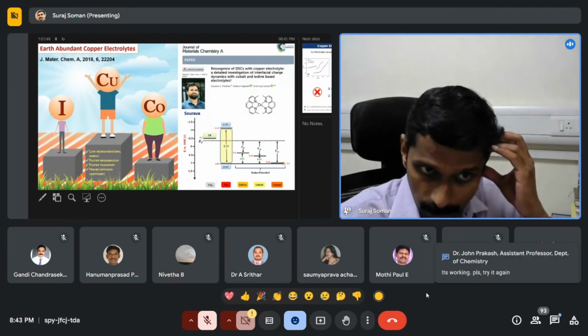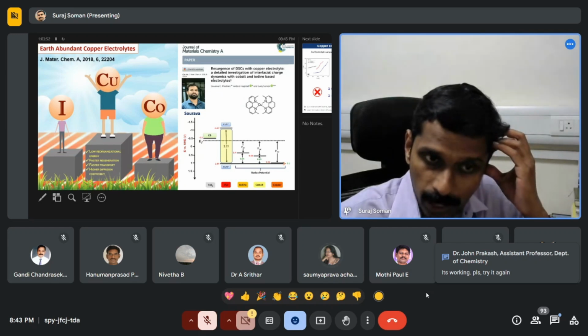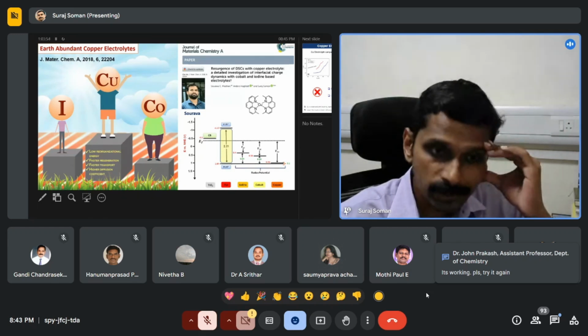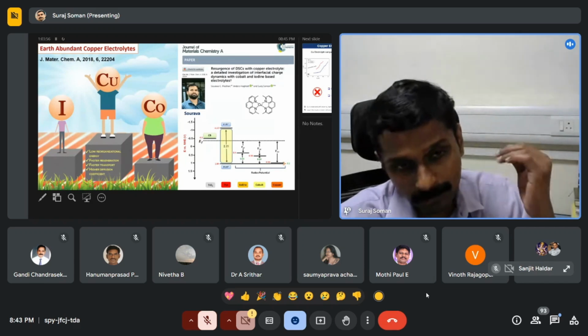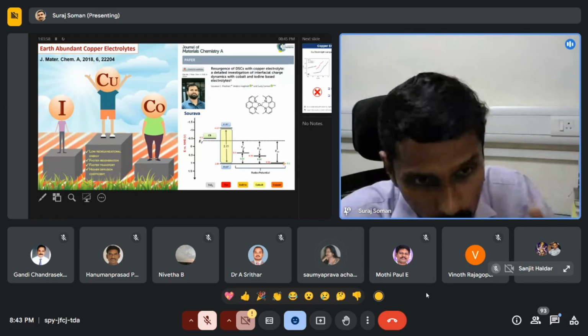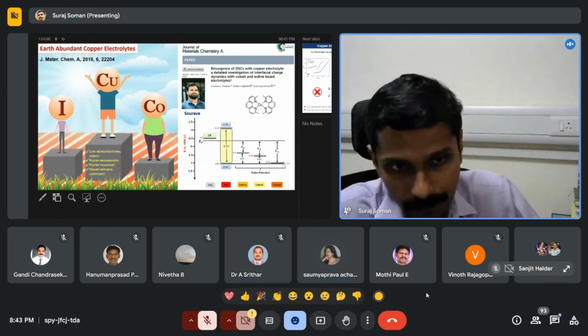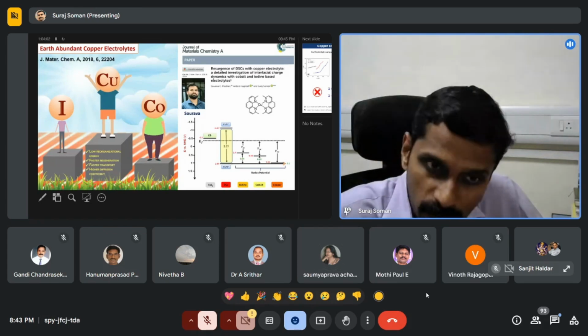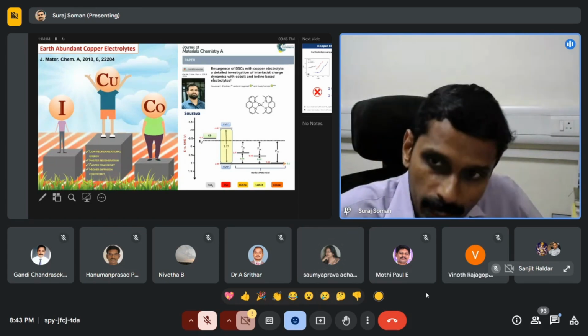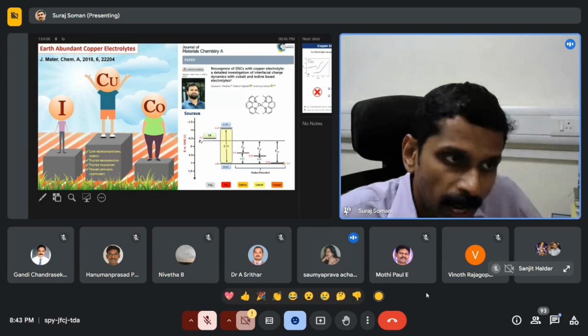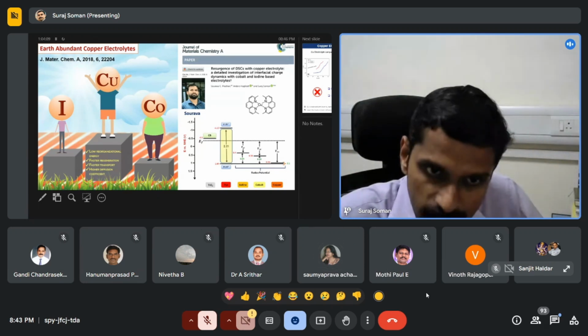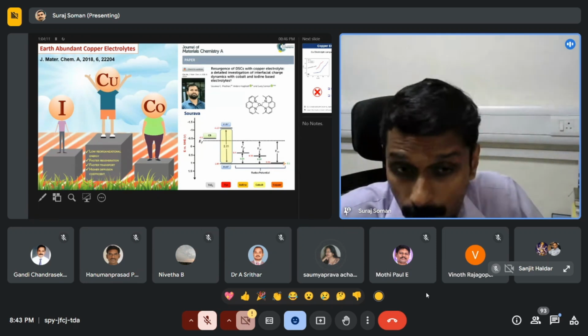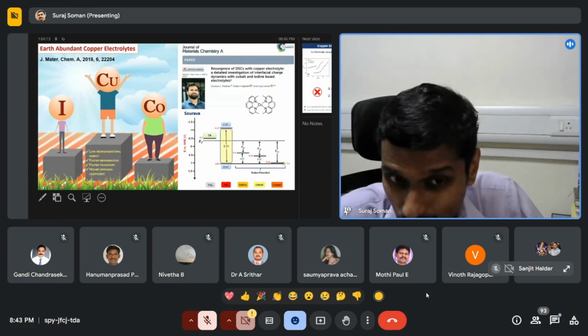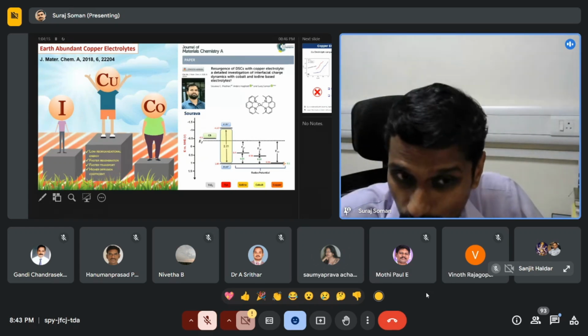So this is the ground state, excited state and the conduction band, and the conventional iodine based system has a redox potential of somewhere around 0.4 volt with respect to the energy. And the moment you move to the cobalt based system, you are again pushing it more positive. You will have it somewhere around 0.56. And the moment you go for copper, your redox potential is again more positive. So you will get somewhere around 0.94.